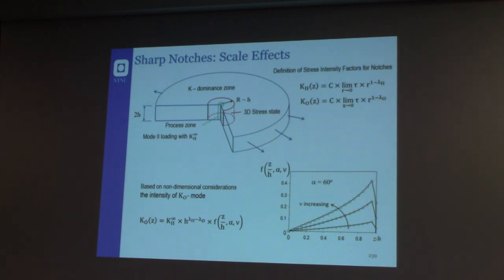This was the finite element model. What happens is that again we find there is a strong influence of the Poisson's ratio. If you increase the Poisson's ratio, you find an increase of the intensity of the coupled mode. And again, the coupled mode is very localized and close to the free surface of the components. Here is the mid plane. In the mid plane, you don't have this effect. So you have a close effect of this induced mode that is very important close to the free surface.